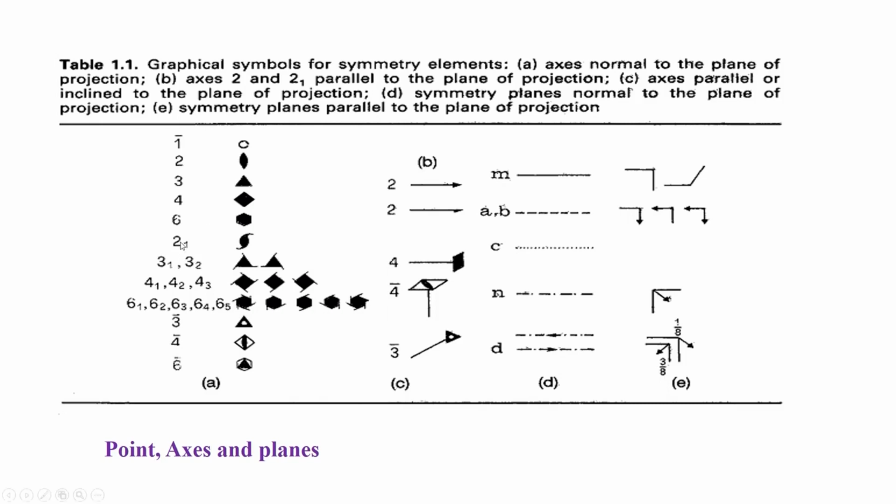Essentially, a 2-fold screw axis is one in which the object undergoes a 2-fold rotation followed by 1/2 the unit translation. So, if our unit cell is defined as A and B, and if this 2-fold axis is with respect to A, let us say, then the 2-fold axis is now doing a rotation of 180 degrees from the position which is now representing the object. So, the object is here, it rotates by 180 degrees, it comes over there, and then it gets translated by